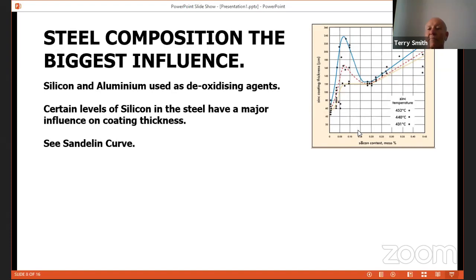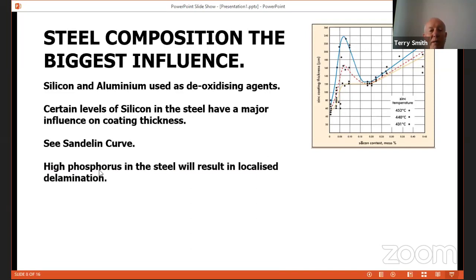Where the silicon is between 0.15 and 0.25, this is really where we want it, which is a nice thick coating without being excessively thick. But you can see at about 0.08% at 450 degrees C what the coating thickness would be like. So high phosphorus in steel will also result in localized delamination.